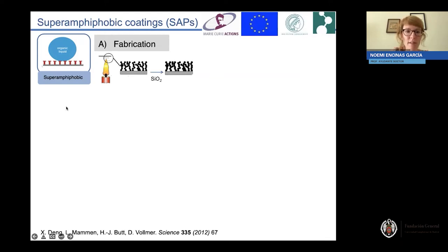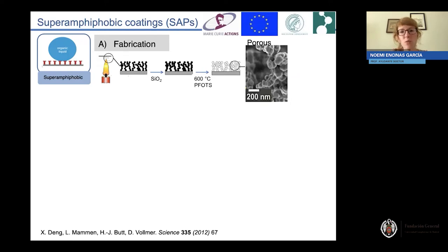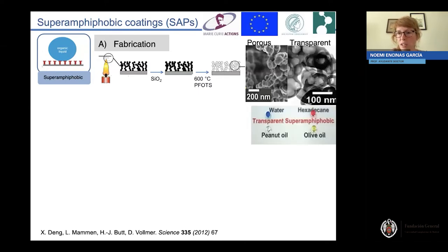So this candle soot template, which was a fractal-like structure that of course presented a really high fragility, was coated by chemical vapor deposition with a silica layer in order to increase this mechanical robustness, let's say. And afterwards the carbon inside was removed by calcination and the surface chemically modified with a perfluorosilane. Of course, as it's formed by silica, it allows basically any type of chemical modification due to the existence of silanol groups. So what they found was a porous-like structure that could be rendered transparent by calcination.